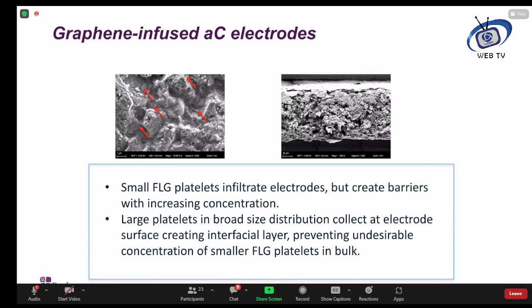So as a result, when you add a normal conductive additive, a carbon black, you tend to reduce the surface area slightly and reduce the specific capacitance of the material, or at least not enhance it significantly. Here, when we add few layer graphene as a conductive additive, we enhance the behavior of the electrode, both in terms of its conductivity, but also in terms of its capacitance.